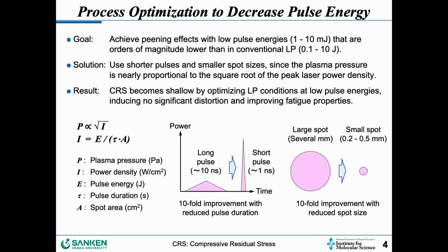However, there are two important things we did. One is to reduce the pulse width, and the other is to reduce the spot size. That increases the peak power intensity, which determines the plasma pressure. So by reducing the pulse width and the spot size, we can keep the peak power intensity, namely the plasma pressure, to induce permanent strain on the material.